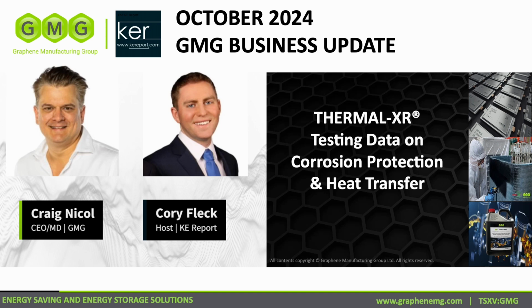So that's one. I think clearly when you're talking about the fan, obviously you're powering the fan, and that heat transfer will happen in a way where you've got forced convection happening with also the radiation from the coating, and so there's less of an impact from the addition of the coating, but it's still a 27% increase in these calculations in this rig that we built and tested. 27% increase is massive in an air conditioner, even with the fan going.